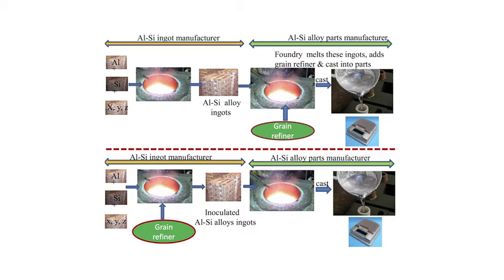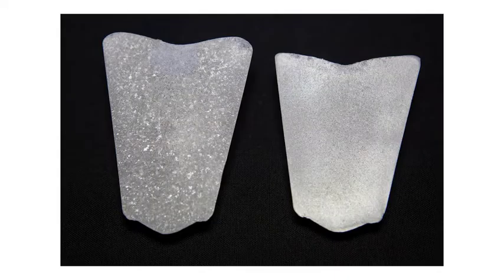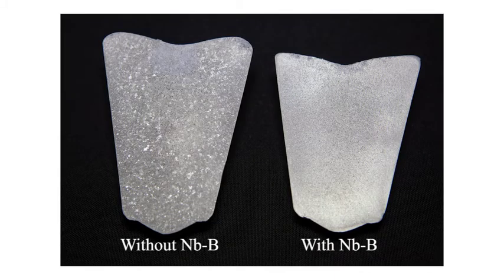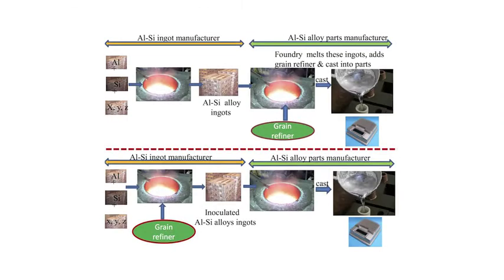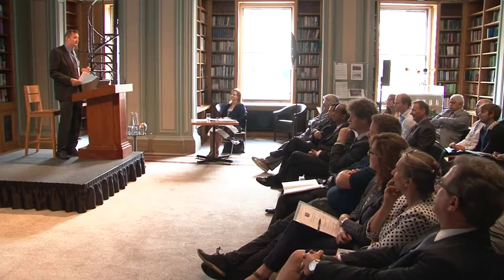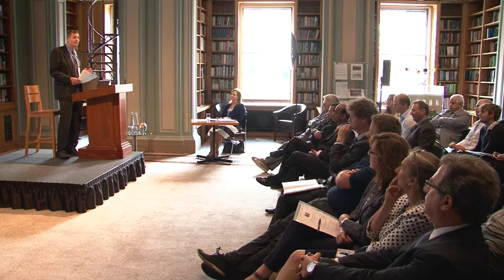He described an industrial trial being carried out to validate the technique and its effectiveness. Norton has demonstrated a production route for A357 ingots with and without niobium boron inoculants. The inoculation has produced significant grain refinement in the ingot, and this persists after subsequent remelting and casting, indicating that the grain refining effect will still be present in the final product. The next step is to optimize the processing conditions for commercial scale production and to produce 20 tons of the aluminium niobium boron master alloy for development trials with potential end users.